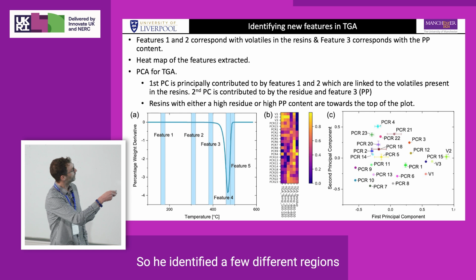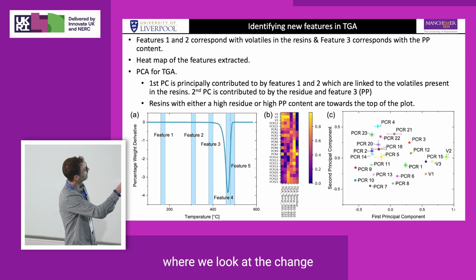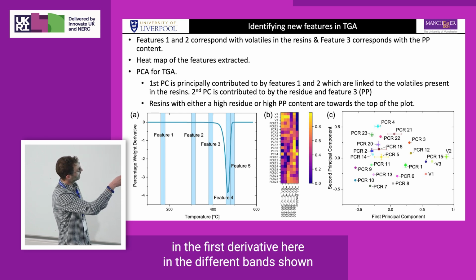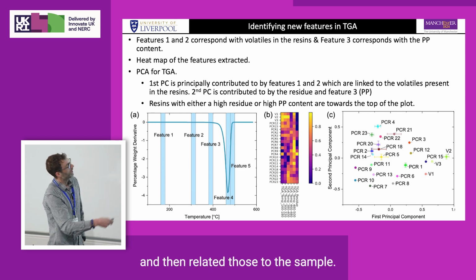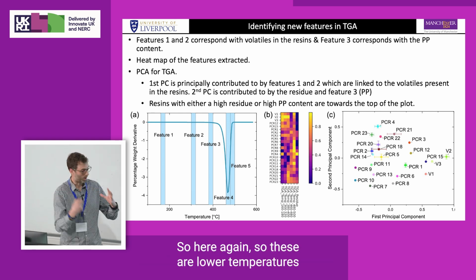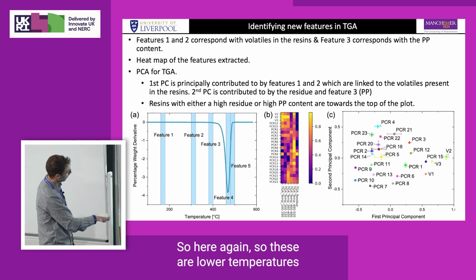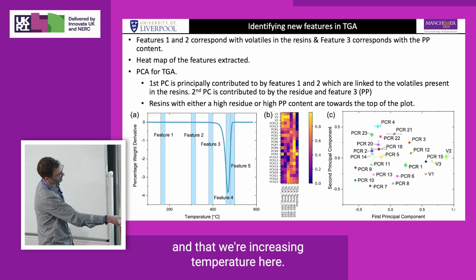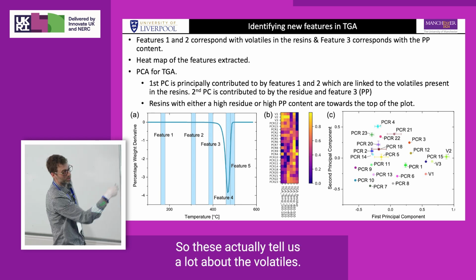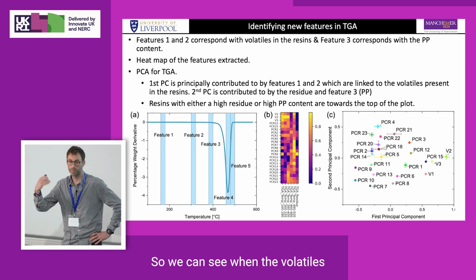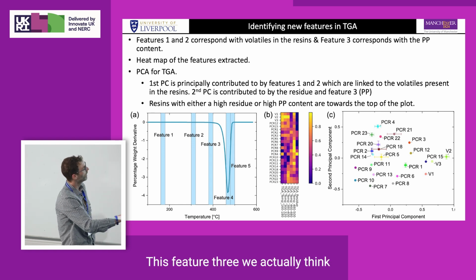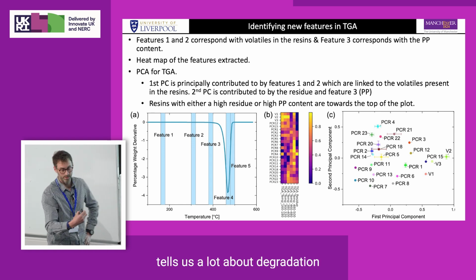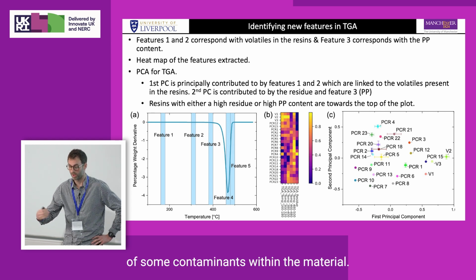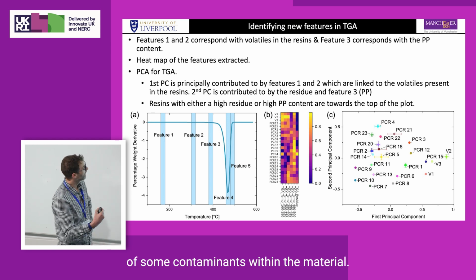So he identified a few different regions where we look at the change in the first derivative here, in the different bands shown, and then related those to the samples. So here again, these are lower temperatures, and then we're increasing temperature here. So these actually tell us a lot about the volatiles. So we can see when the volatiles are being lost from the sample. This feature 3, we actually think tells us a lot about degradation of some contaminants within the material.